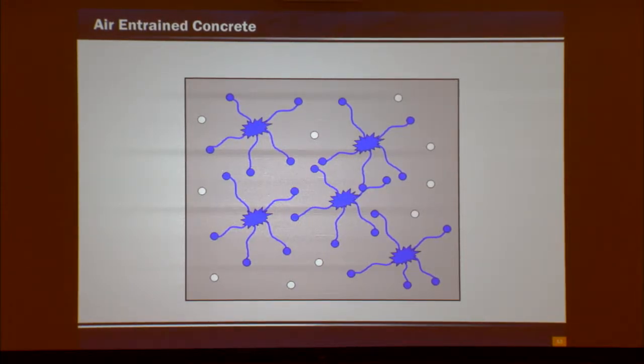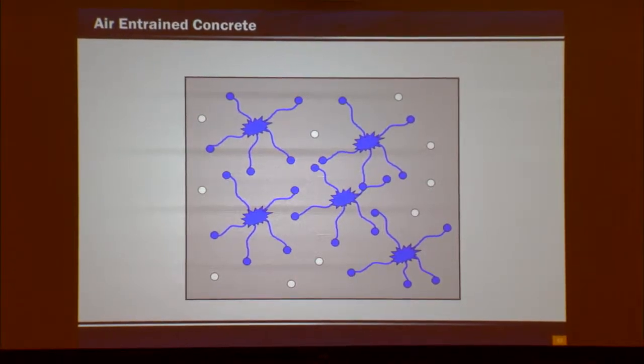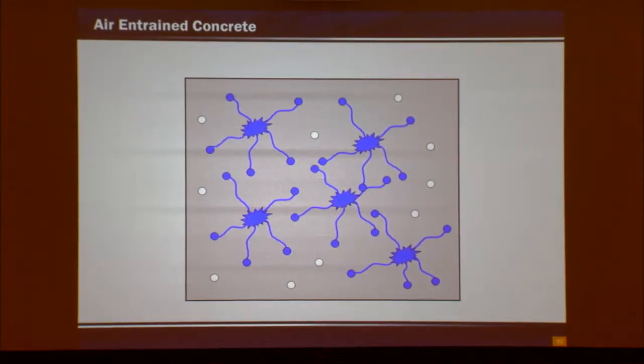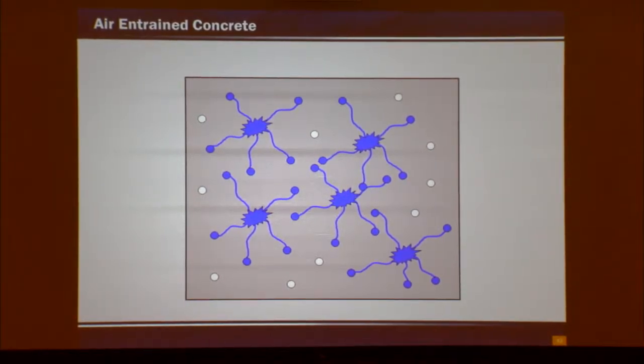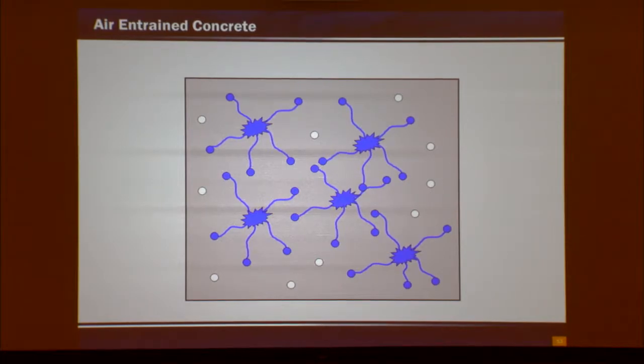Pretty simple. The problem is trying to get the bubbles at the right spacing, and I can tell you air content isn't always the best way to measure freeze-thaw durability, because you can have coarse air, 5%, but your spacing factor is way off. So people are working on trying to measure spacing factors in fresh concrete. And I think they're close. I think we're doing it now. So that's something that we will probably look at implementing in the future as well.